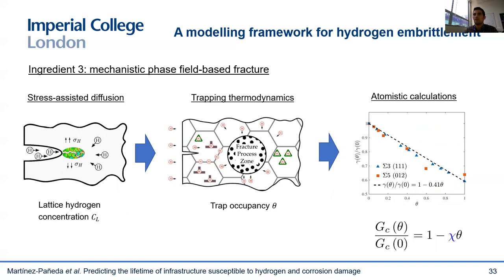To summarize, we have developed a coupled deformation-diffusion-fracture platform which builds upon the phase field fracture method and a mechanistic, implicitly multi-scale hydrogen degradation law. The steps are: first, solve the coupled mechanical-diffusion problem to know how much hydrogen we have, where and when. Then use Oriani's trapping model to determine the occupancy of the critical interface, for example grain boundaries. Then go to atomistic calculations run offline to determine how much the fracture energy is degraded — all without any fitting parameter. The phase field hydrogen degradation law is essentially a DFT relation between fracture energy and hydrogen coverage.